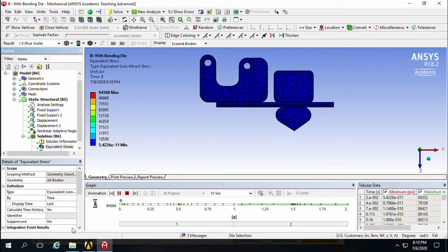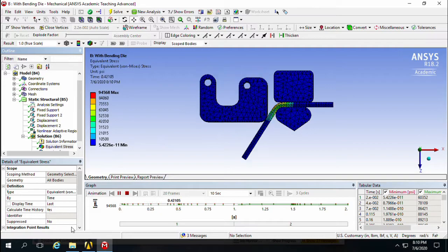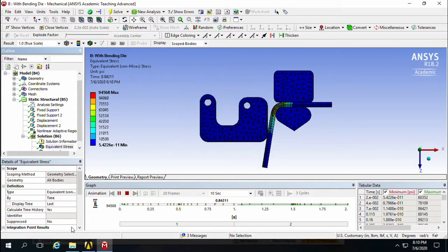The prototype was first modeled on SOLIDWORKS with key dimensions that would be used within the actual design. The ANSYS simulation used the imported SOLIDWORKS geometry and was set up to solve large deformations with multilinear isotropic hardening properties. The supplier of the rod material conducted a tensile test for the 4140 hexagonal steel rod. The nonlinear region of the stress strain results was entered into the simulation to account for the nonlinear yielding properties.